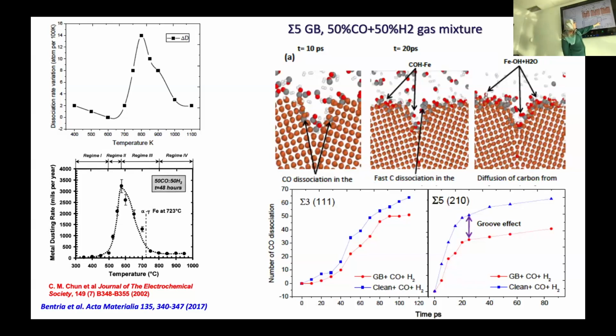And here, for example, when you have the groove, you see that in this case you have an enhancement of the number of CO molecules that are dissociated. This can be understood from the point of view that you have more catalytic sites that are accessible, where CO dissociation is happening. So this is just to give you an idea.